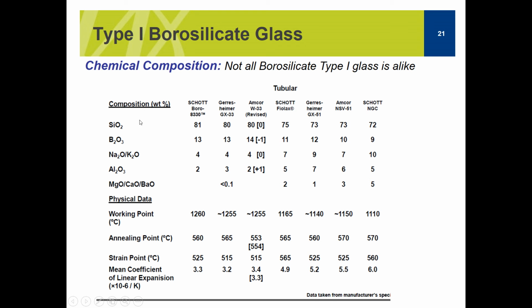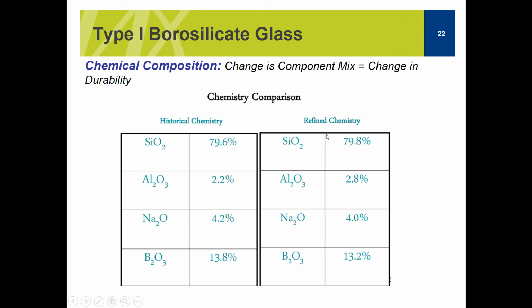And in general, the higher the SiO2 content, or silicon oxide, the better the glass. So this is an example of the different type 1 glass formulations, and the companies that have them. Now that begs a question: does changing this chemical structure have an effect on extractables and leachables, and does it have an effect on delamination? And the answer is yes. If we change the chemical structure, we will change the likelihood of a vial experiencing delamination. So in this experiment, what Gerresheimer did is they changed the chemical composition of glass.